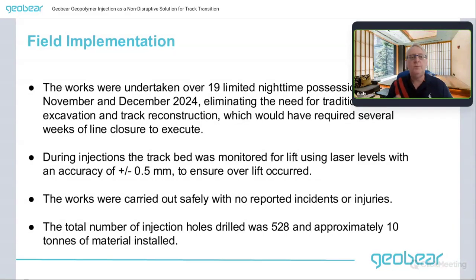So in terms of field implementation, these works were undertaken over 19 limited nighttime possessions during November and December 24, eliminating the need for traditional excavation and track reconstruction, which would have required several weeks of line closures to execute. During the injections, the track bed was monitored for lift using laser levels within an accuracy of 0.5 millimeter to ensure no overlift occurred. The works were carried out safely with no reported injuries or incidents.